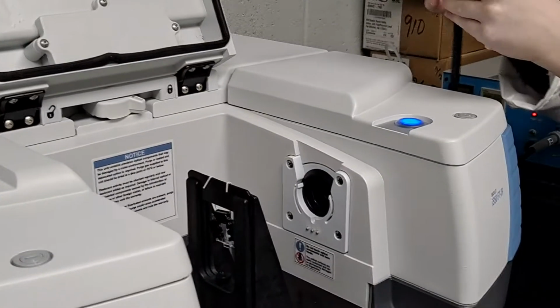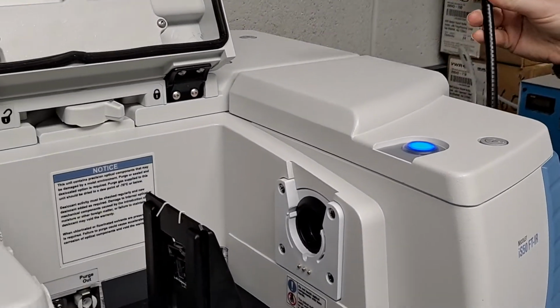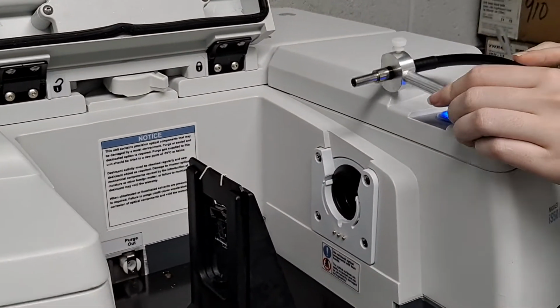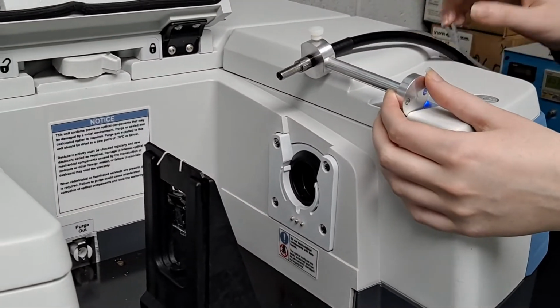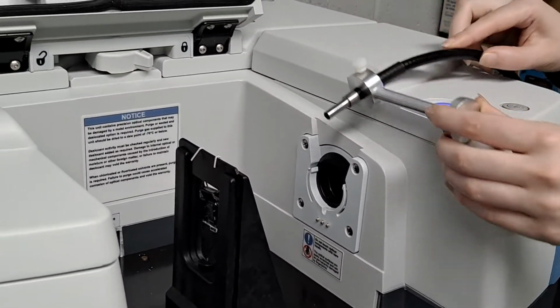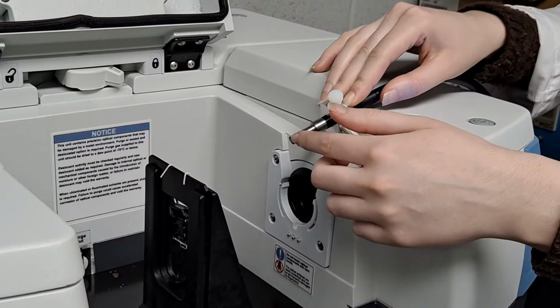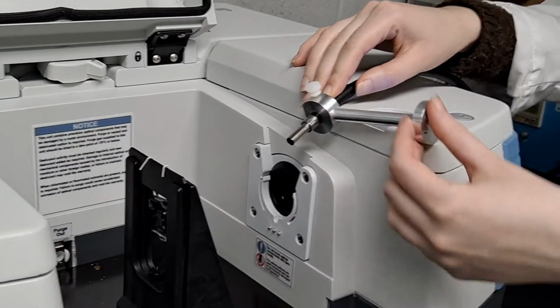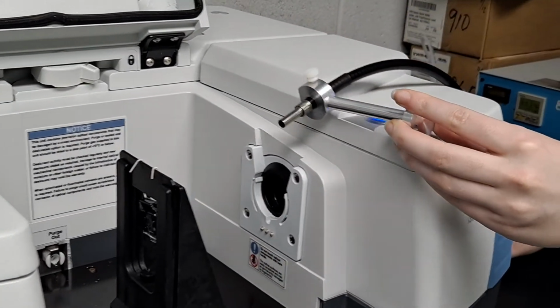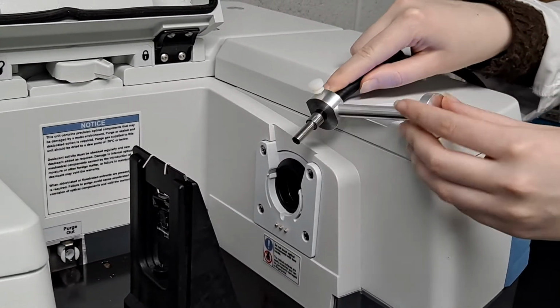So what intensity are you going to use? 0.03 watts per centimeter squared. The lamp comes here. You'll want to make sure that it's angled to where it'll hit your sample. So this could take several tries to get it right.